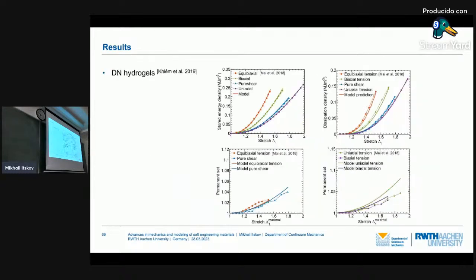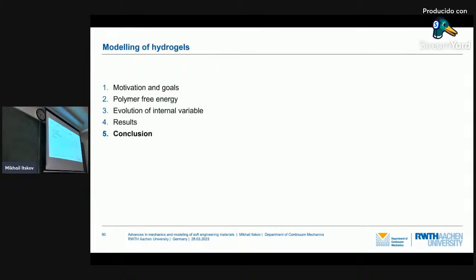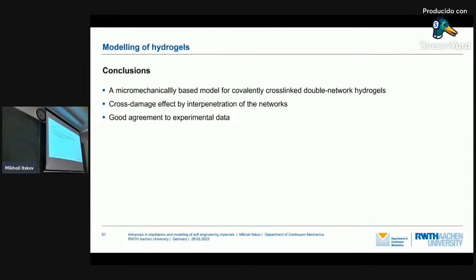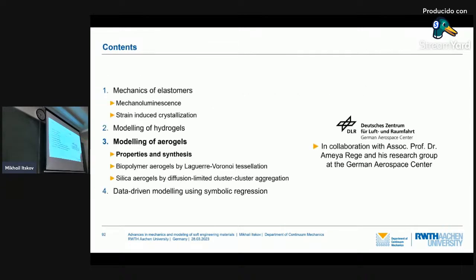pure shear, biaxial tension. Also here other results for double network hydrogels, for the stored energy, dissipated energy density, and permanent set. Also the agreement is rather good. Right. Some results of the study. So we proposed here a micromechanically based model for covalently cross-linked double network hydrogels, and the challenge was to take into account this cross damage effect, as already mentioned, and we obtained good agreement.